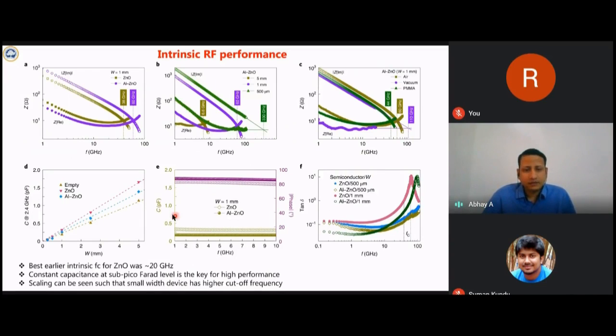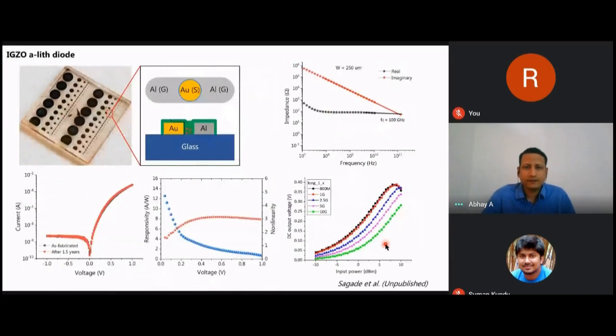This is because the junction capacitance of the device is very stable up to 10 gigahertz, because this is the limit of measurement, and it has been found very flat. Corresponding to that, the tan delta, which is a loss, is also found to be very minimal, and that's why the diodes have been seen to work at higher cutoff frequency.